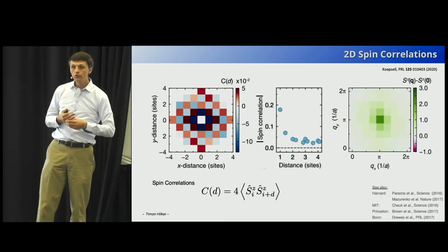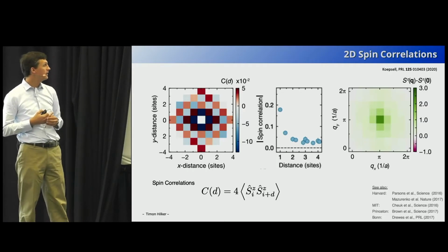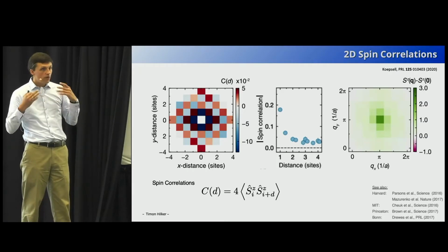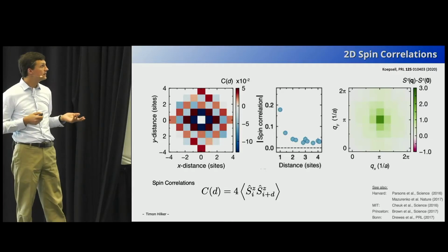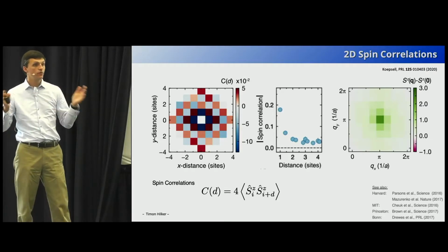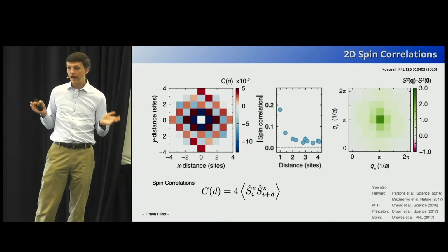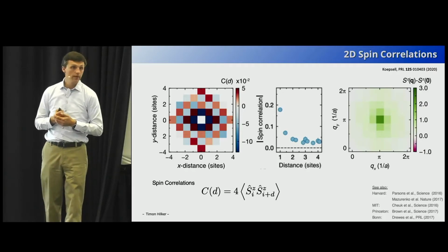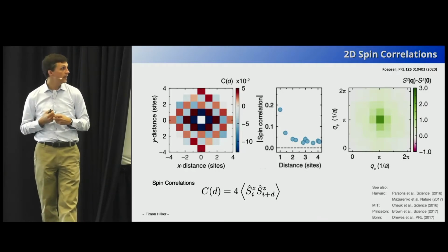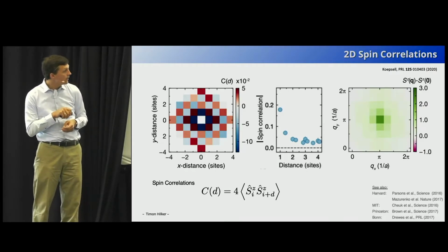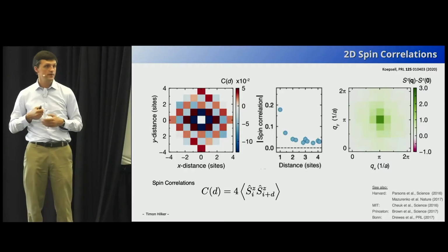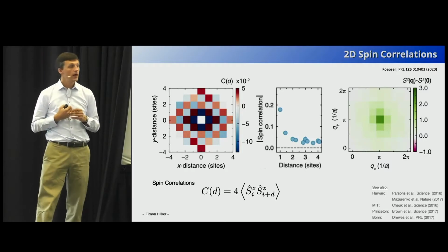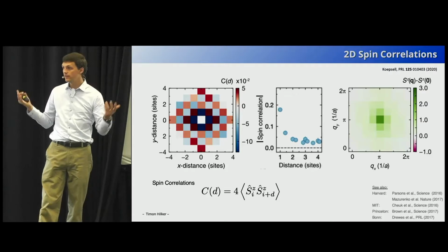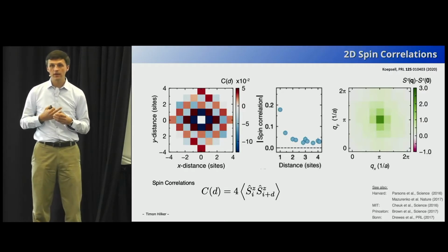We can do the same in 2D, so we see clear antiferromagnetic finite range correlations in these systems. They can actually spread through the entire system. If we typically have system sizes of maybe 7 by 7 or up to 10 by 10, then one basically sees a weak correlation that stretches through the entire system, even at finite temperatures, because there are some finite size effects coming in here.